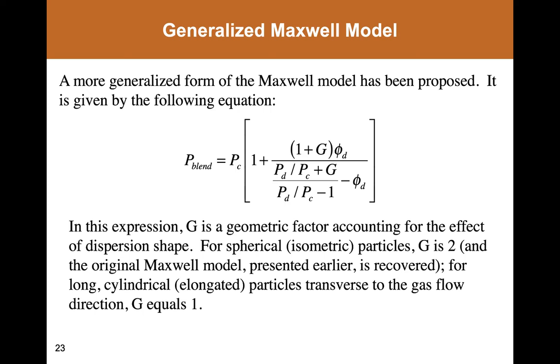And so another model that is used to describe transport in heterophase materials is the generalized Maxwell model. So the original Maxwell model is typically taken to apply to spherical dispersion of particles in a polymer matrix. The modification of the Maxwell model introduces a geometric factor G, and this gives a measure for the effect of the shape of the dispersed particles on transport properties.